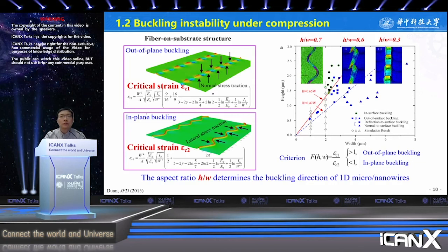The simplest method is to calculate the system energy of the fiber-on-substrate structure. Then one can get the critical strain of the two buckling modes, respectively. Now, we can establish a criterion to judge which buckling mode appears. The criterion is equal to the ratio of the two critical strains. When it's larger than 1, out-of-plane buckling appears. Otherwise, in-plane buckling appears.